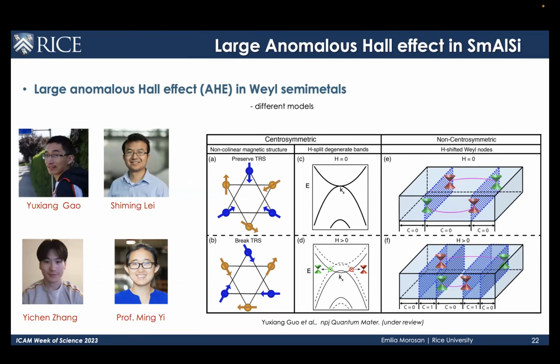So what this basically means is that in the absence of an applied magnetic field, so with time reversal, the Weyl nodes sit at opposite momenta in reciprocal space, such that the chiral, the Chern number is 0 everywhere in the Brillouin zone. But when you apply a magnetic field, the existing Weyl nodes are shifted such that they're no longer at opposite momenta in reciprocal space, and this gives rise to non-zero Chern number regions, and that is what creates the Berry curvature, which in turn is responsible for anomalous Hall.